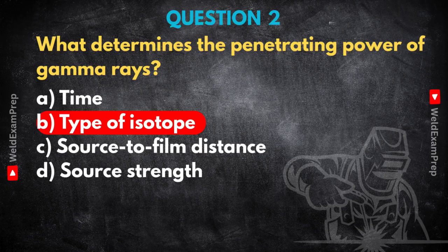You wouldn't use iridium-192 for, say, really thick steel, maybe over 70 or 80 millimeters. Its energy just isn't high enough. And if you tried, you'd end up with incredibly long exposure times, which isn't great for safety. And worse, you might completely miss deep flaws that a higher energy source, like cobalt-60, would show you quite easily. So choosing the right isotope is critical for both efficiency and actually finding what you need to find. Exactly, matching the energy to the job.